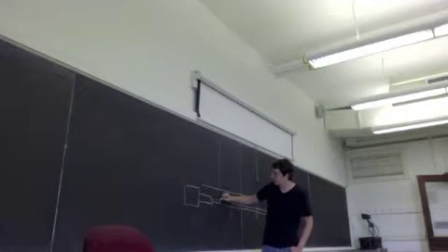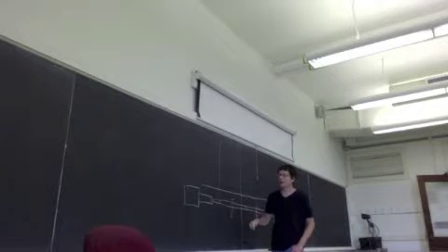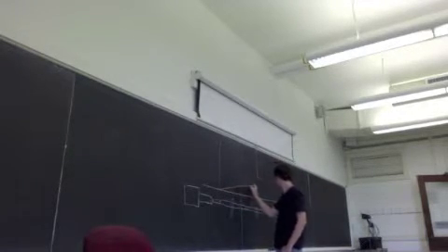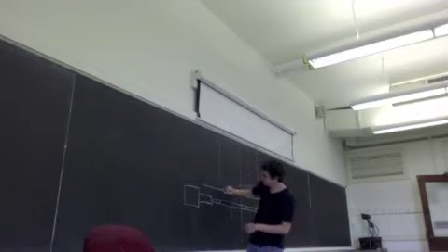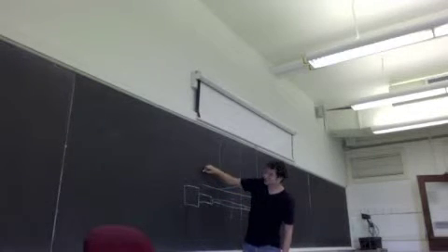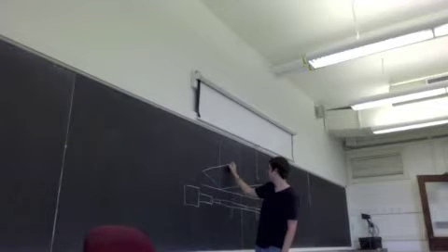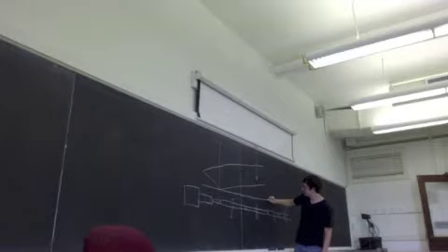So, as the projectile strikes the end of the incident, or the first bar before the sample, two waves are generated. One travels down the incident bar. Another one travels back from the point of impact along the projectile. When it hits the end of the projectile, it reflects and then travels back to the end and into the incident bar. When it hits the sample,